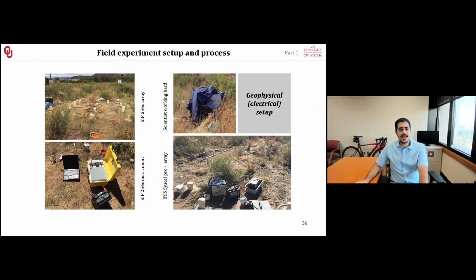We used a SIP 256C instrument from Radic Research, Germany, for measuring complex conductivity. We used an IRIS Syscal Pro capable of doing resistivity and time domain measurements at around 4 Hertz for our time domain and resistivity measurements. And we did everything on 3 lines for the time domain measurements and 2 lines for the SIP measurements.